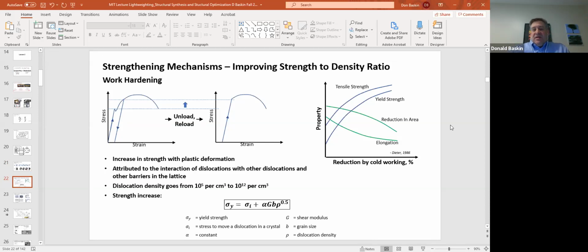One way to improve the strength to density ratio of a metal is through what's called work hardening. I'm sure you guys have seen stress strain diagrams. You have a linear region where, as you load up a component made of a metal, the amount of deformation that occurs is directly proportional to the amount of stress you put in. It's a linear relationship. As you keep increasing, eventually the material is going to hit what's called the yield strength. And then the stress strain curve keeps going up, meaning that as you apply more strain to the material, it's going to keep getting harder and harder to create more strain. The stress is going to go up, and the yield strength of the material continues to go up.